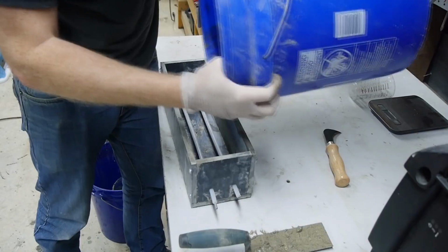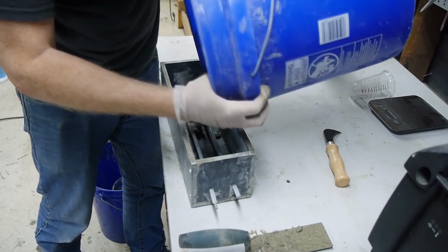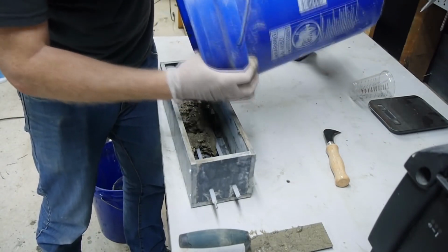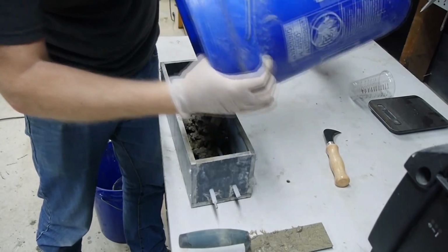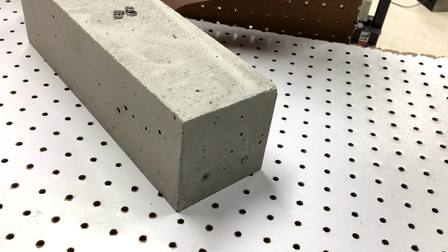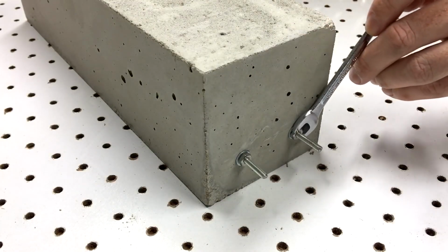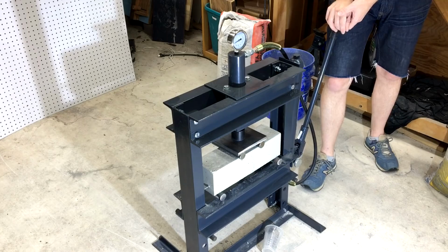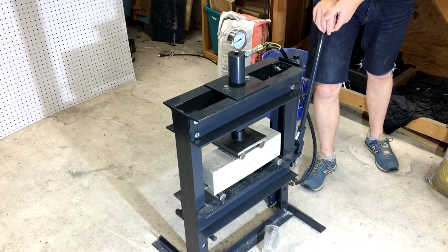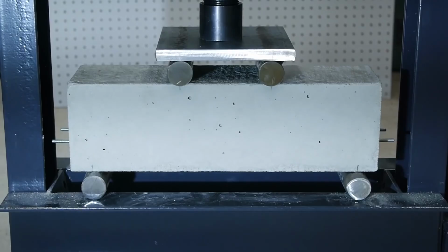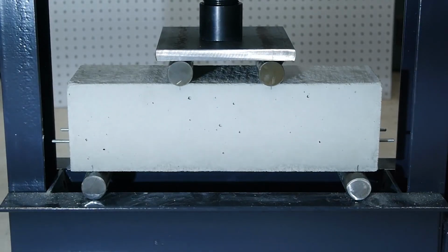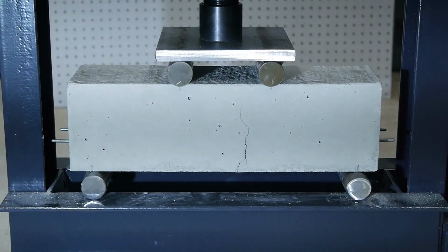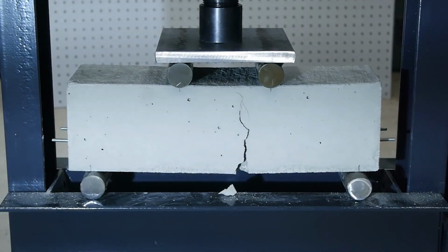Another way to pre-stress reinforcement is called post-tensioning. In this method, the stress in the reinforcement is developed after the concrete is cured. For this next sample, I cast plastic sleeves into the concrete. The steel rods can slide smoothly in these sleeves. Once the beam cured, I tighten nuts onto the rods to tension them. Under the press, this beam wasn't any stronger than the conventionally reinforced beam, but it did take more pressure before the cracks formed. Also, this one wasn't quite as dramatic because instead of failing the actual steel rods, it was the threads on the nuts that failed first.